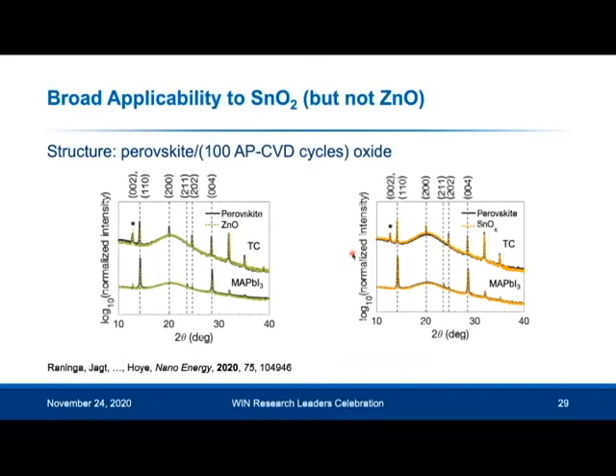So now that we have some very promising results with TiO2, we wanted to see whether APCVD could be more broadly applicable. And so here we're looking at tin oxide and also zinc oxide, which are both N-type oxides. And here we grow the oxides directly onto the perovskites, so both methylammonium lead iodide and triple cation perovskite thin films. And we looked at the diffraction patterns, and we saw that when we grew the zinc oxide, there was the appearance of extra lead iodide. And this is consistent with the literature, which suggests that zinc oxide could interact with the perovskite to deprotonate and cause degradation. There's also literature that suggests that the diethyl zinc metal precursor for the zinc oxide can degrade the perovskite itself.